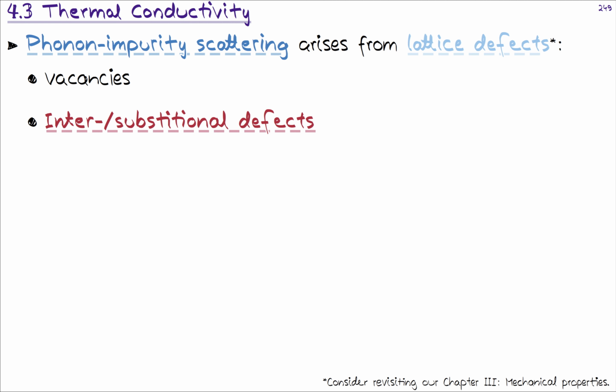And then one example of a substitutional defect would be an isotopic change in the atoms. So, for example, with respect to my favorite material, diamond, even though we do not usually think about it, a diamond is not isotopically pure. In normal diamonds, around 1% of the atoms are actually C13 isotopes and not C12. Because the mass of our atom is now different, when we look at phonons, lattice vibrations, we see that this is actually an impurity. And this affects things. Interestingly enough, you can isotopically purify materials, and that actually affects the thermal conductivity. So this can be experimentally verified that this is indeed a mechanism, and that is known.